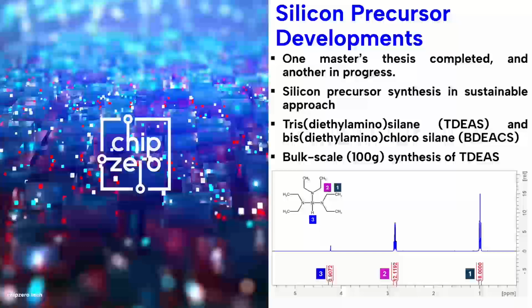We chose 3 precursors in the beginning: TDEAS, tris(diethylamino)silane, then tris(dimethylamino)silane, and also bis(diethylamino)chlorosilane. We were successful in developing 2 precursors, TDEAS and BDEACS. For TDEAS, we were even able to scale up the process to more than 100 grams already, so we are able to produce this in the large quantities required for the semiconductor industry. Here I just show NMR results showing the successful synthesis of this precursor.